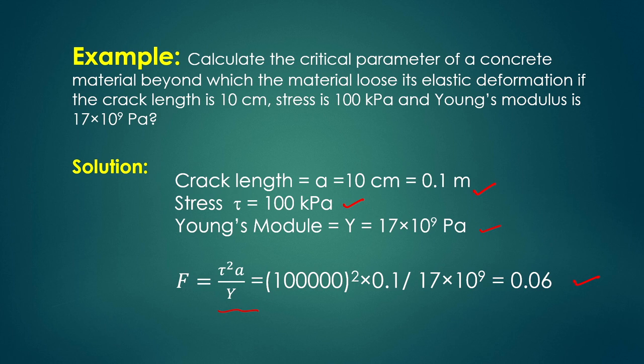That will be equal to tau square a by Y. That will be equal to tau, 100 kPa whole square, then into 0.1, that is the a value, divided by the Y value 17 into 10 to the power 9. So after calculation, you will get this value as 0.06. So this is the critical parameter, 0.06. Beyond this critical value, the concrete will be cracked into smaller pieces. Okay, so this is the critical parameter that you have to know.